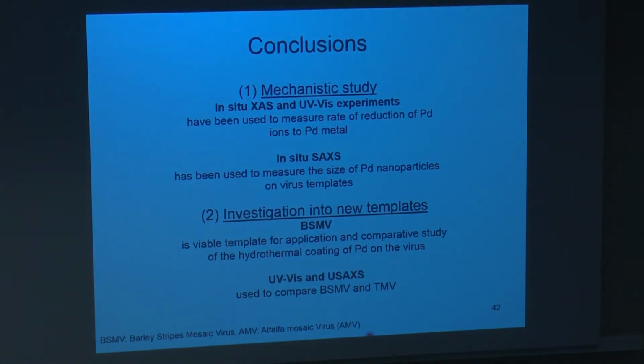biotemplate. So the conclusions from this work, using in situ X-ray absorption spectroscopy and UV-Vis experiments, we were able to determine the kinetics of reduction of palladium on the plant virus. And also, using in situ SAXS, we can measure the size of these palladium nanoparticles and basically how they evolve over time during the reaction. We're also investigating the coating of BSMV, and it behaves a lot like TMV. And so we've used the UV-Vis and SAXS, and we're analyzing the data now to compare the BSMV and the TMV in terms of palladium reduction on these two biotemplates.